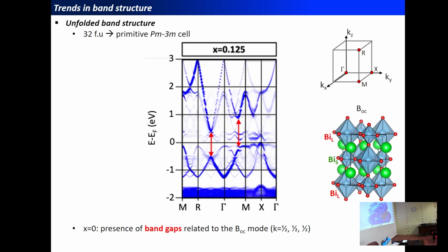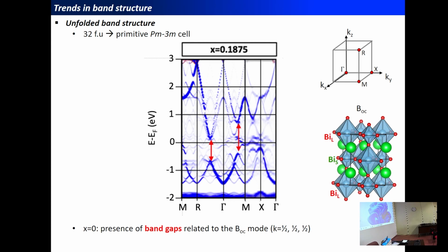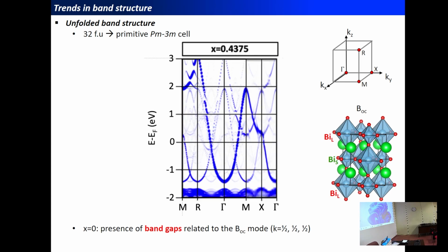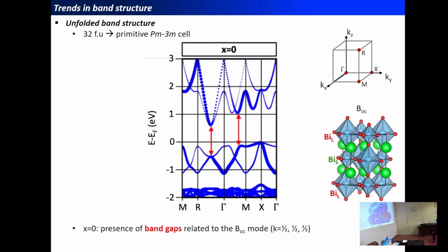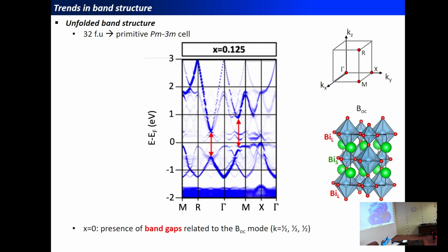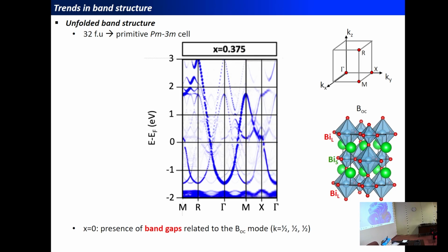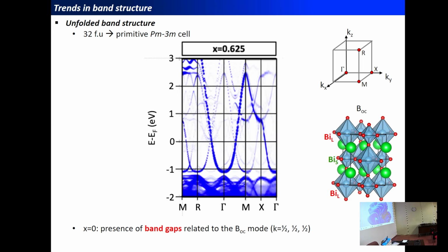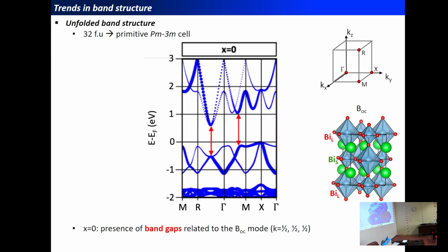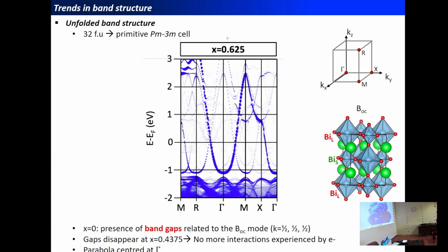If we put more holes in the material, you see that the band gaps are closing until they totally disappear. And so this is compatible with what we have observed from the point of view of the electronic density of states. The charge ordering is likely disappearing in the material, and so we lose the gap once we reach a doping content of 43.75%, meaning that at this moment we are left with a single parabola reminiscent of a free electron system in which very likely there is no more interactions experienced by the electrons in this system.